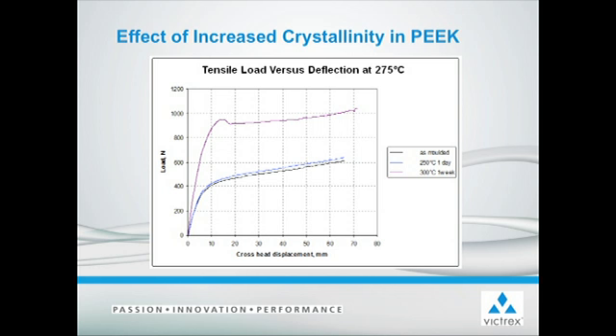This plot shows how the mechanical performance of PEEK can be enhanced with annealing. You'll see a slight increase in the tensile strength when annealing occurs below the application temperature, but a significant improvement when the annealing occurs above the application temperature.